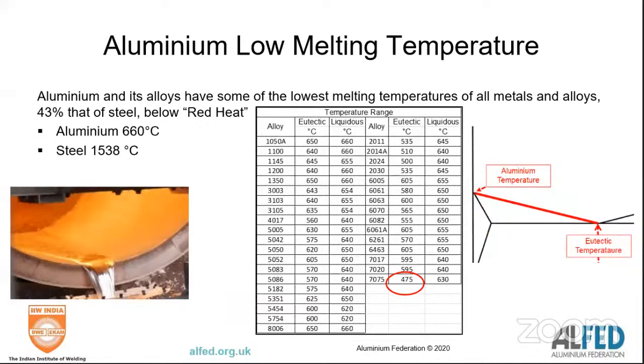Pick out an important property. Aluminium's got low melting points. Pure aluminium melts at 660 degrees C. If you look at the higher aluminium alloys, they have low melting points, down to about eutectic temperatures of 450, 470 degrees C. So it's a very low melting point metal. At 450, 500, you're below red heat. So very low melting temperatures. That has implications in that we don't form scales, we don't need complex tooling, we've not got thermal losses, we've not got radiation losses. So it's a plus and a minus.